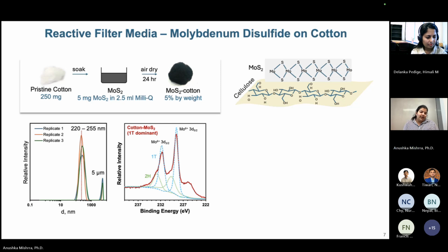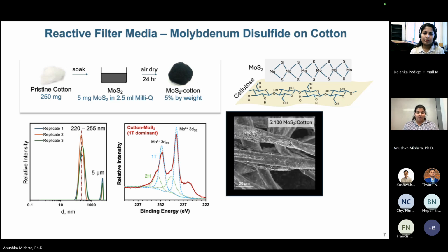We also wanted to make sure that during the synthesis process, we did not lose the phase that we want. So we can control the type of phase we want for the MOS2. We just create that phase first and then run the synthesis of the MOS2 cotton, so we did not lose much of it. We have still retained the MOS2's 1T dominant phase on the structure. We did this analysis using XPS.